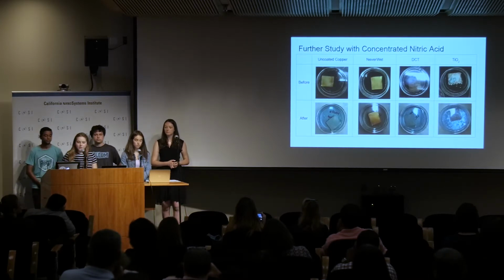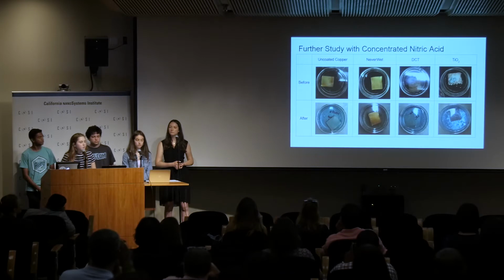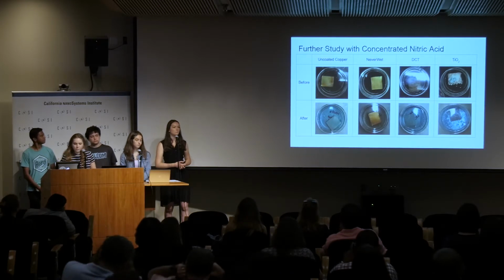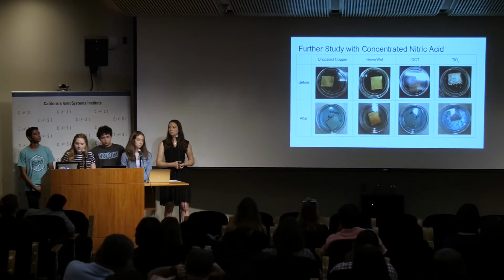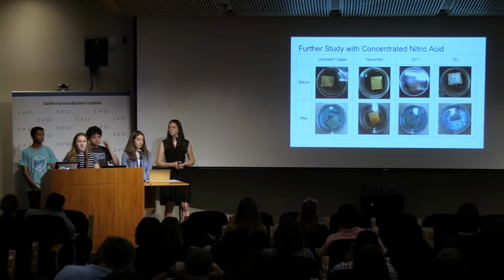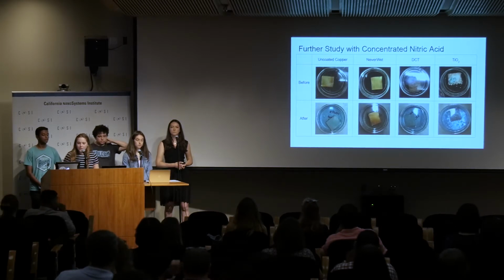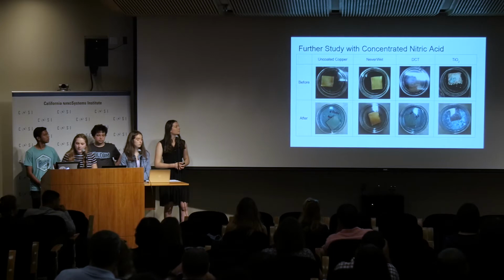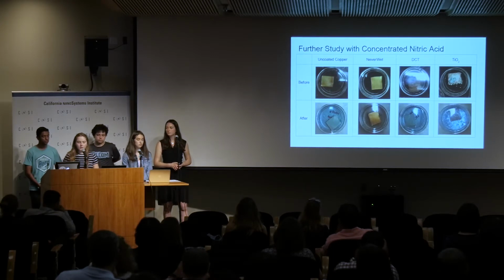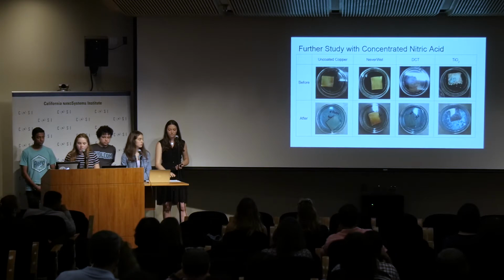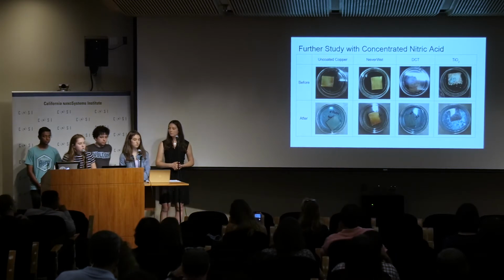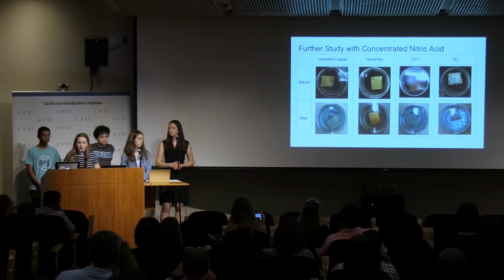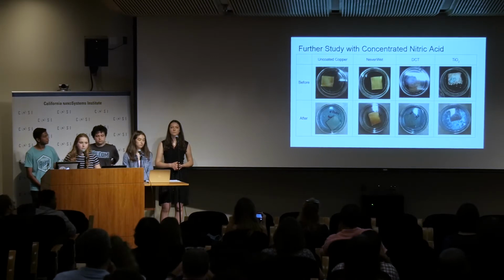Okay, so we conducted a further study with the nitric acid to represent long-term corrosion in the limited time frame that we had, which is 2 days. We can see that the nitric acid in fact reacted with the uncoated copper, DCT, and TiO2, except for the NeverWet. The TiO2 and the DCT in fact became hydrophilic, but the NeverWet stayed hydrophobic.